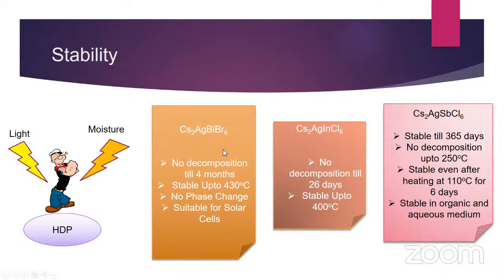So for Cs2AgBiBr6, those are stable up to 4 months. They are stable up to 430 degrees centigrade. There is no phase change, and they are suitable for solar cells. And for the Cs2AgInCl6, there is no decomposition till 26 days, and they are stable up to 400 degrees.